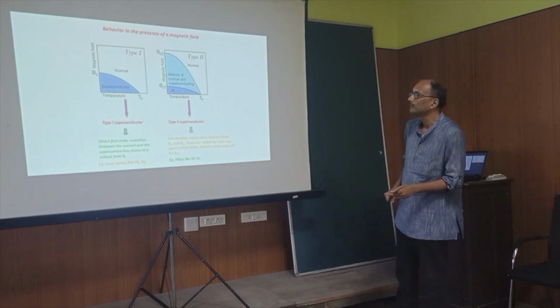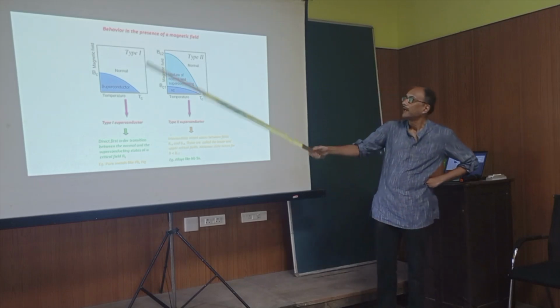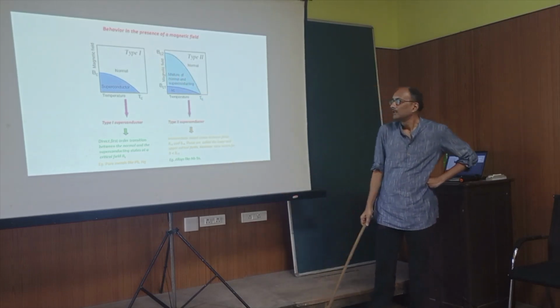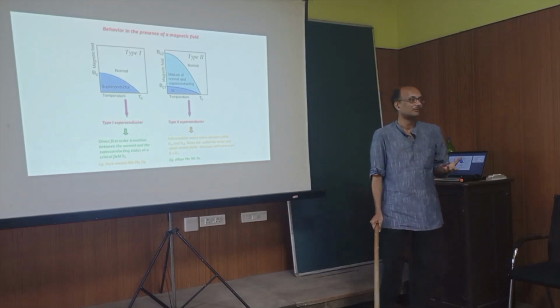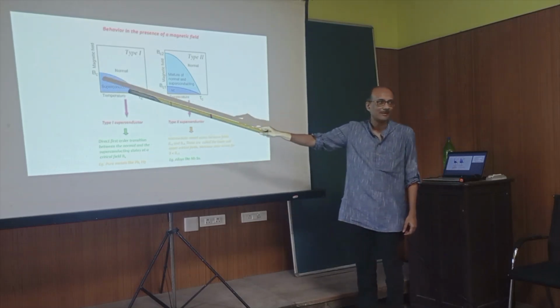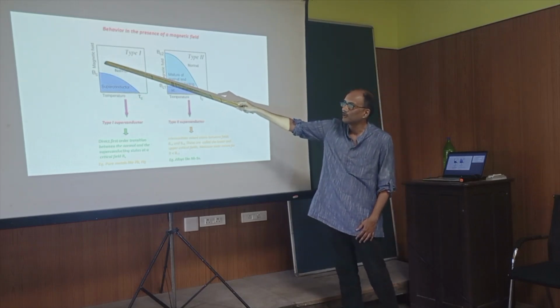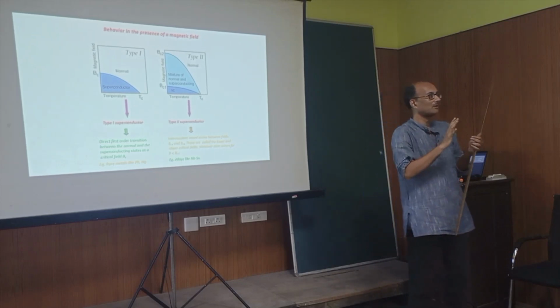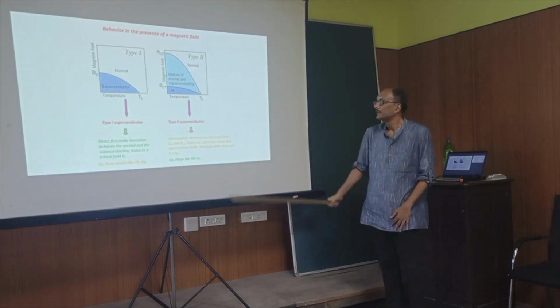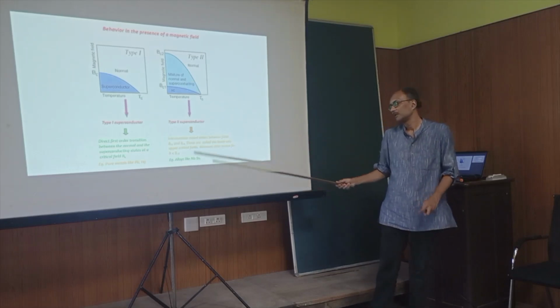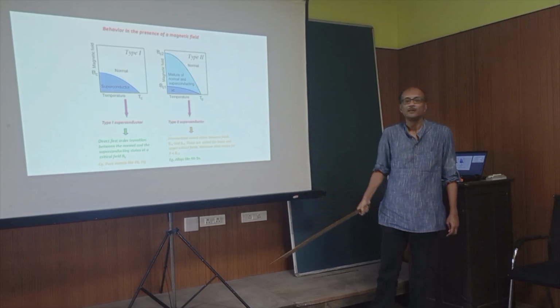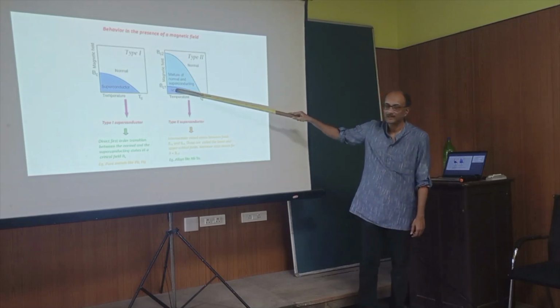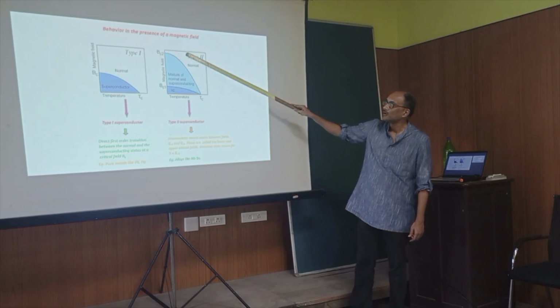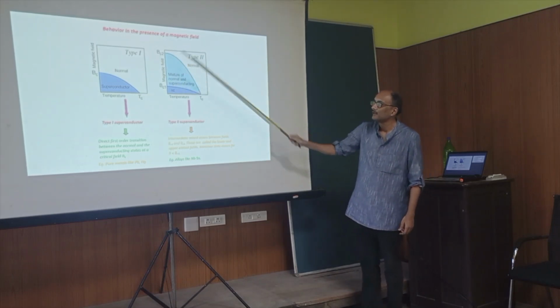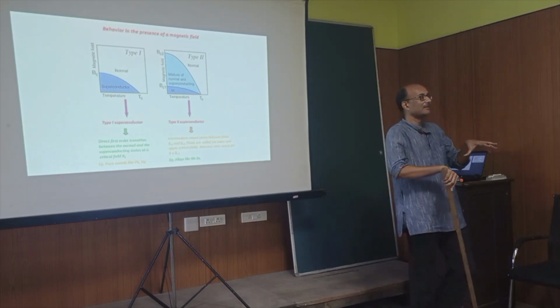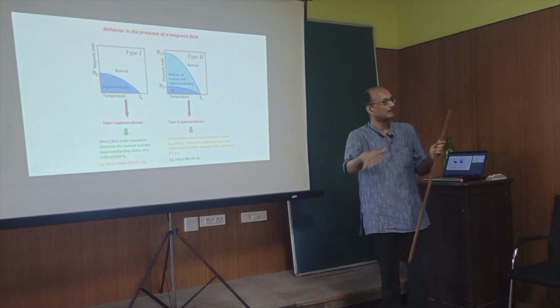So people also looked into the behavior of superconductors in magnetic fields, and what they found is that there are two distinct types. So pure metals like lead or mercury, when you cool them, it so happens that if you put in a magnetic field, there is a critical field above which it goes to a normal state. So if you put too much of a field, the superconductor just gets destroyed. However, for alloys like alloys of niobium or other things, what happens is that you start from a garden variety superconductor out here, but then you don't immediately go to a normal state. There is an intermediate phase where there is some region inside the sample which is metallic and some other region which is superconducting, so it's a mixture.